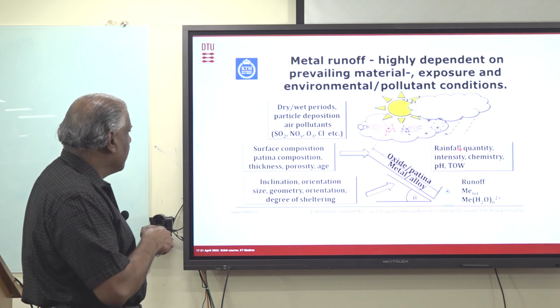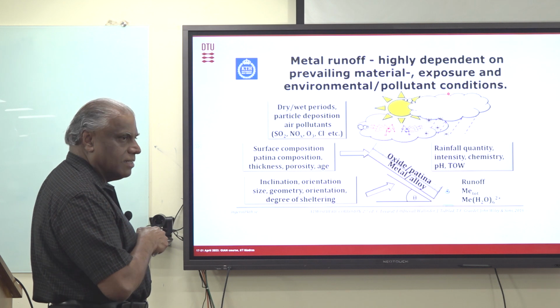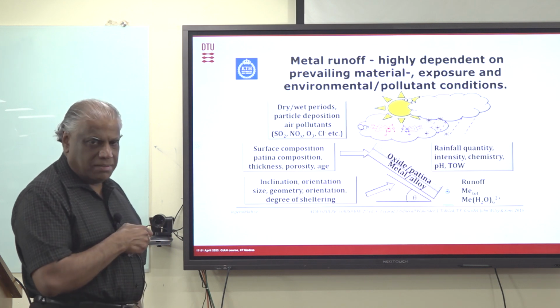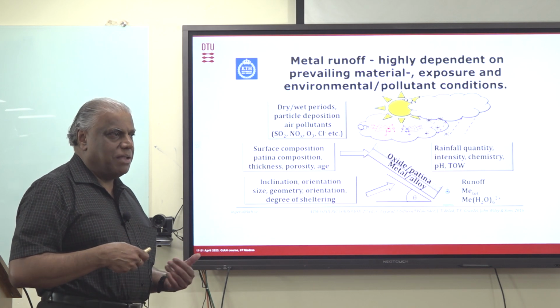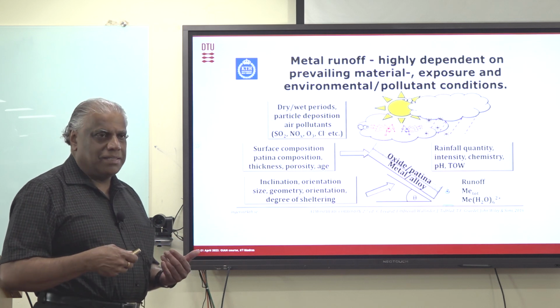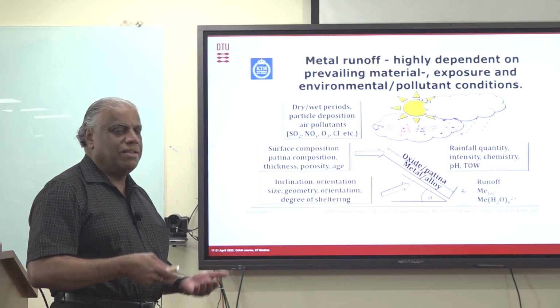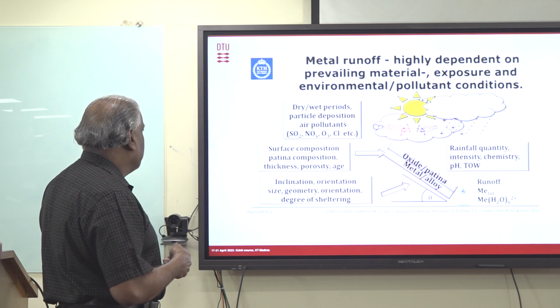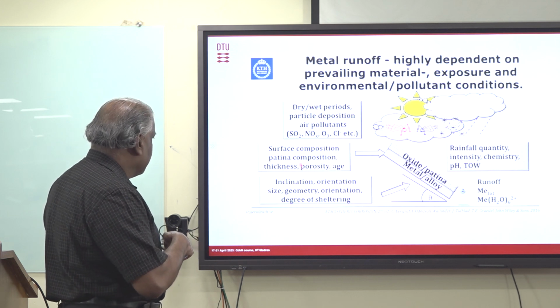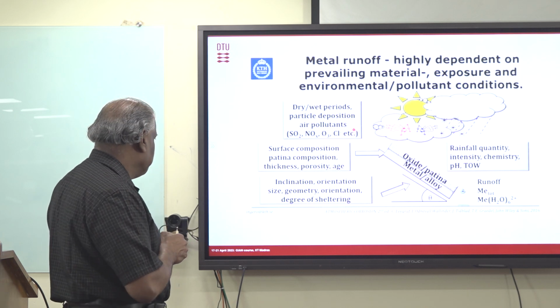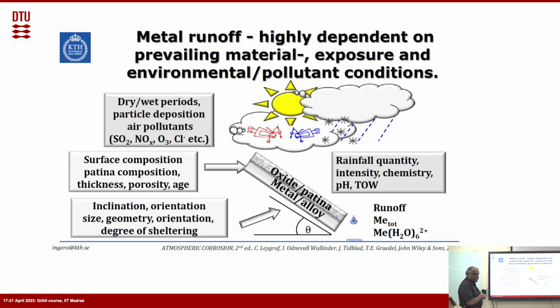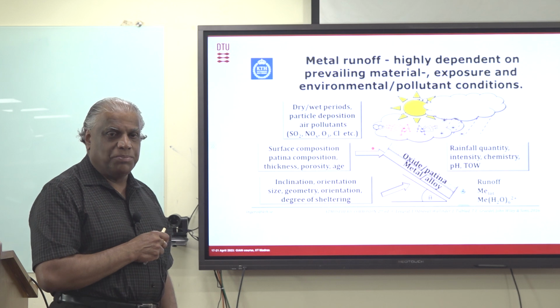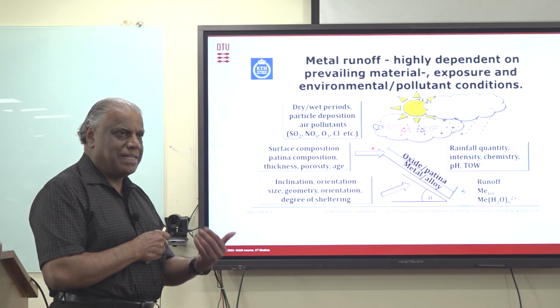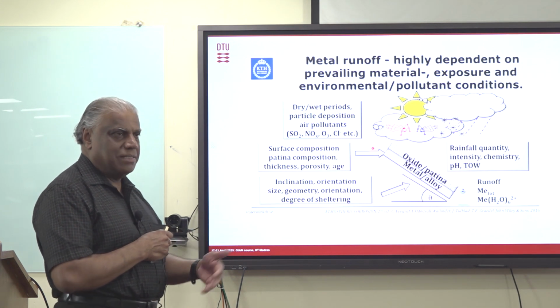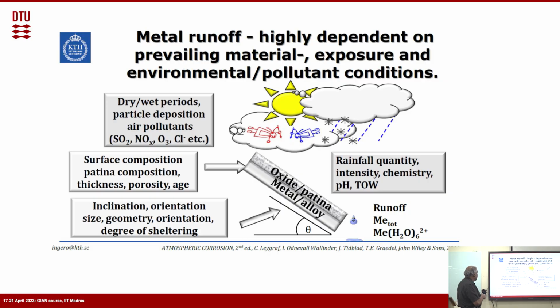Then they also found that the metal runoff is highly dependent on the prevailing material exposure and environmental pollution conditions. That means the dry-wet period is important. There is a dry period where pollution, aerosols and things like that, which also contain salt, are deposited. Then when there is a wet condition, that increases this dissolution. All these gases and other species in the environment are important. Surface composition of the patina depends on the metal, and the patina composition, porosity and age are important, because if the patina is porous, not only will the patina dissolve, but the environment will also attack the copper. I'm taking copper as an example, but the meaning is the same for all metals.